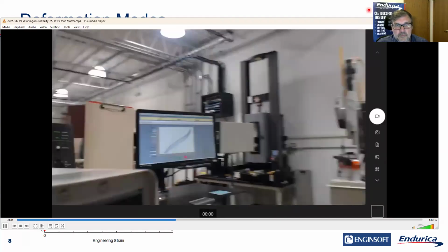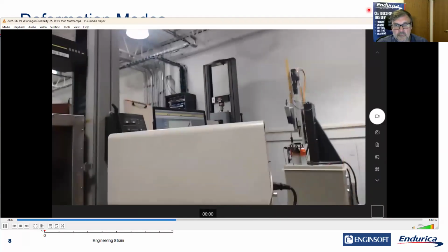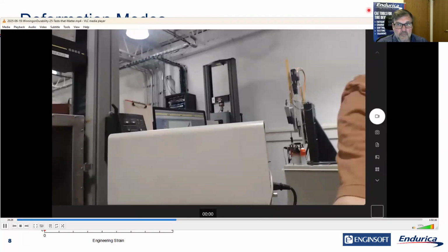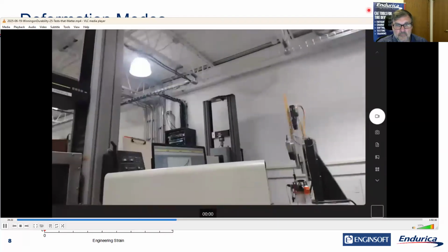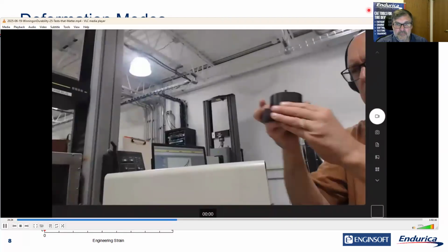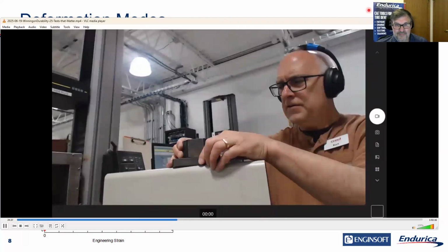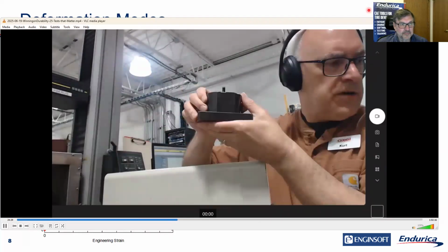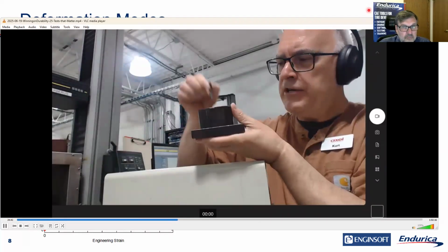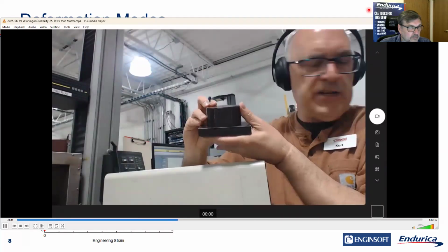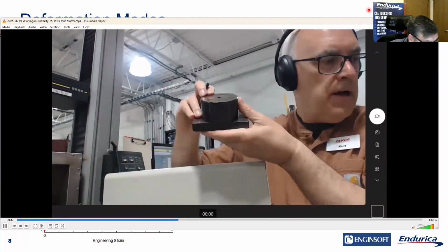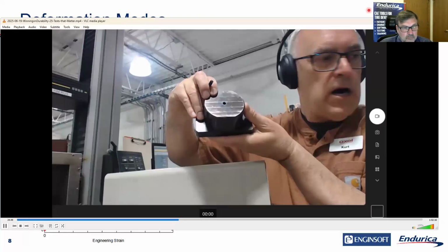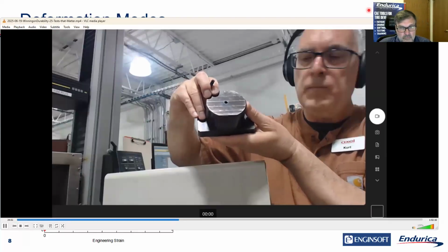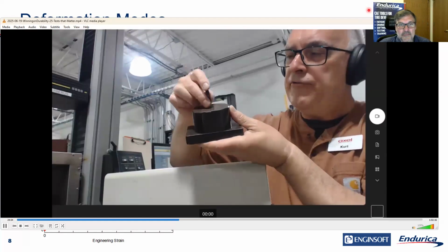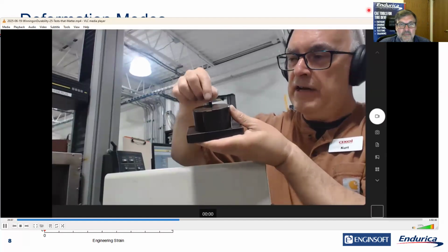All right. I'm going to show another test, kind of a strange way, because it's actually not much to see anyway. This is a fixture that we use for the bulk modulus test, or the volumetric compression test. We take little discs of rubber and we just stuff them into that little hole on top. Then we take a plunger which fits perfectly. You can see it's an air fit. It doesn't even drop in because it bounces on air.